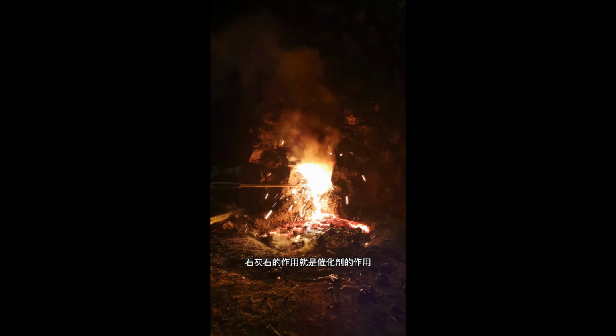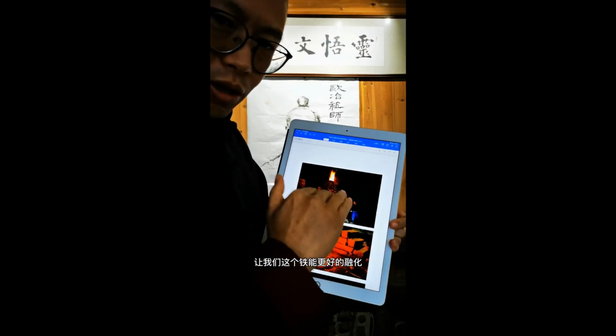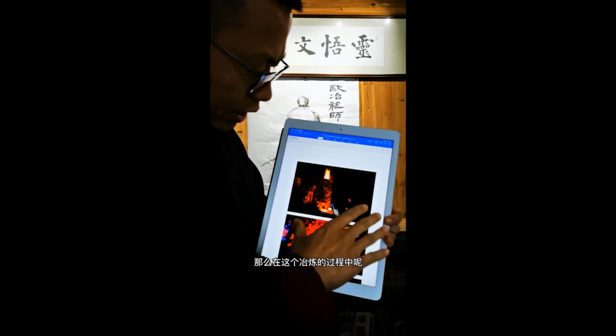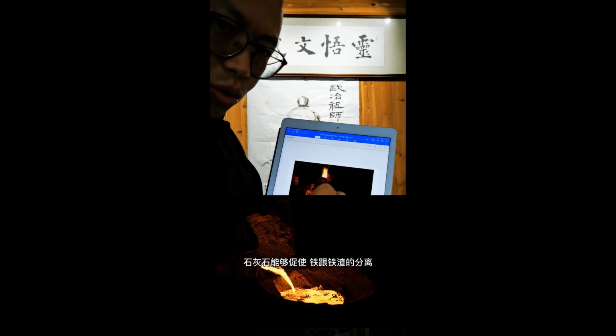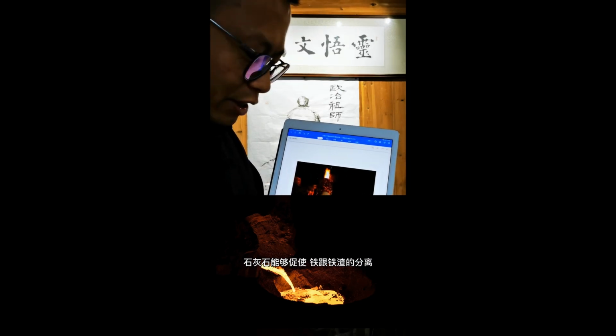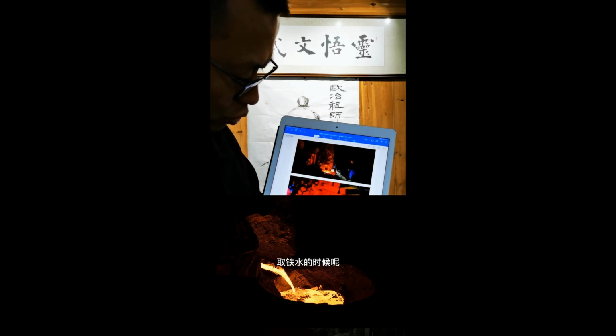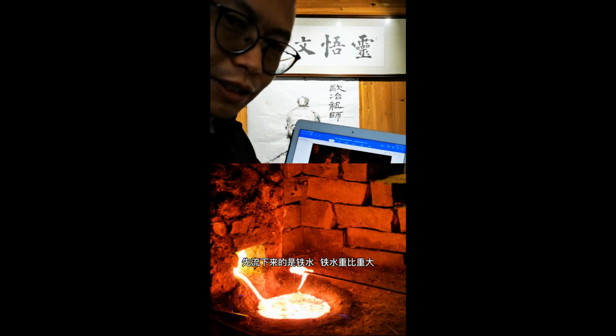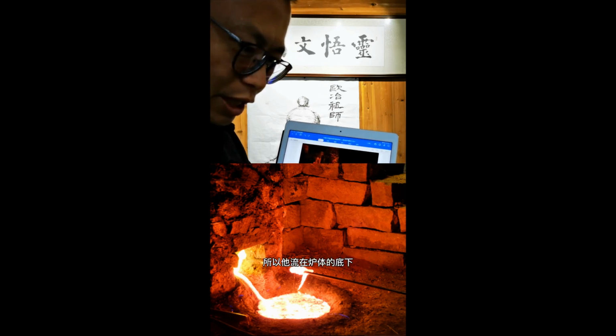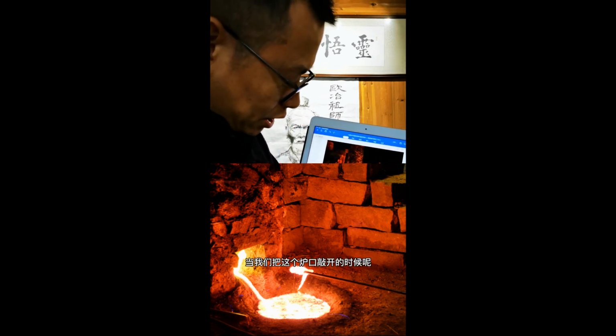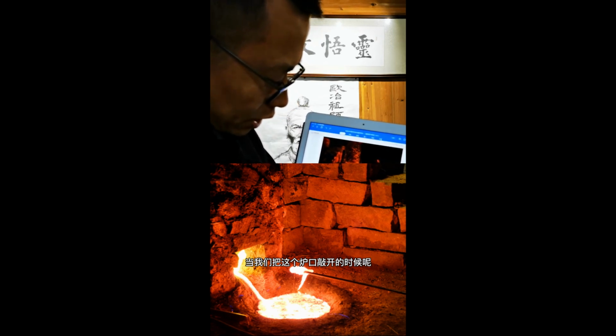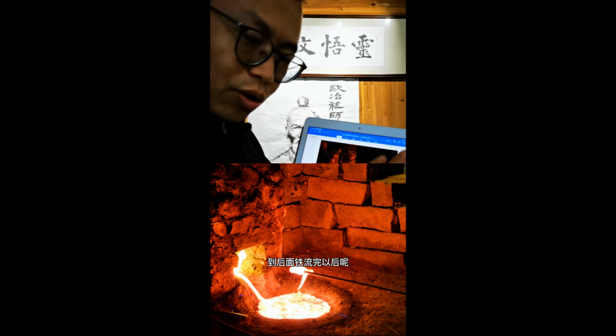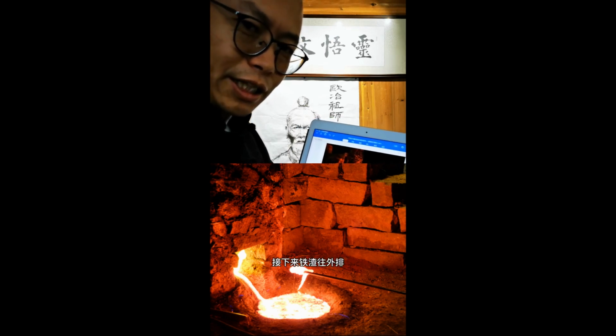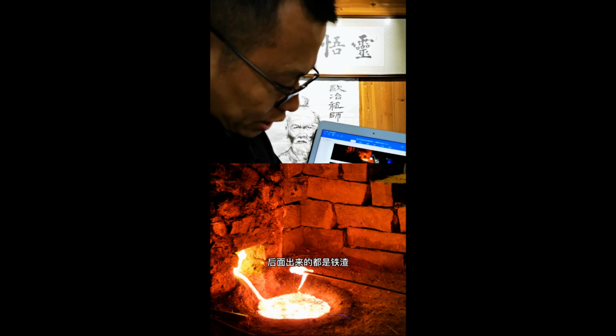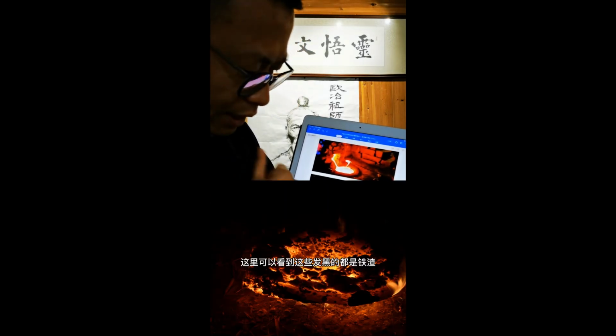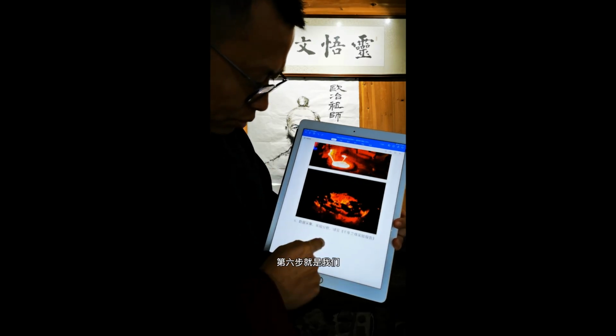We also use limestone. The purpose of limestone is just like a catalyst, so that the iron can be melted better. During the smelting period, limestone can also help with the separation of iron versus slag. So when we got the melted iron out, the slag would stay in the furnace without flowing first. We opened the hole, and the melted iron would flow out first. And after that, the slag would flow out. You can see here, the darkened areas are the slag.